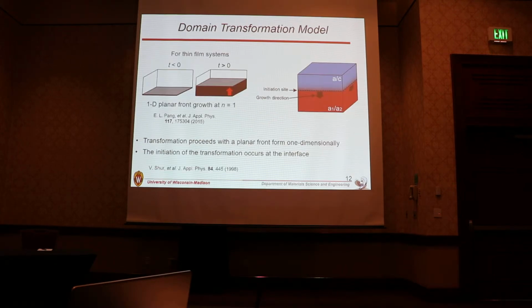And the dimensionality close to 1 indicates the growth mechanism is the one-dimensional planar front mechanism. So Dr. Pang performed molecular dynamics simulations to understand the growth mechanism in a thin film system. And he found that the dimensionality of 1 means that the nucleation occurs on the surface of the system and makes a one-dimensional planar front, and then the growth direction is along the out-of-plane direction through the sample.